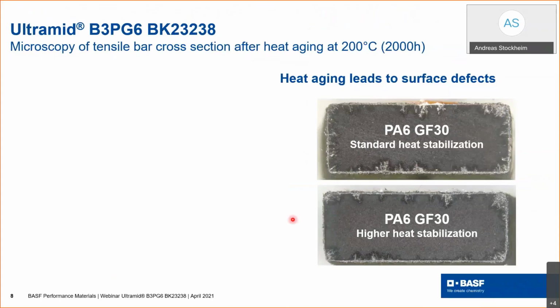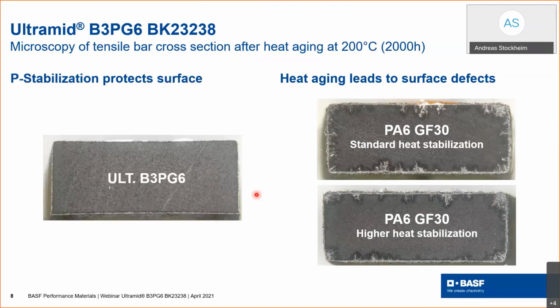And below here, you can see the PA6 GF30 with a higher heat stabilization, the cut tensile bar, where the surface is slightly more protected and the defects are not that strong. And here you can see our new B3PG6, where the surface really protects the tensile bar, where you can more or less not see any defects on the tensile bar.